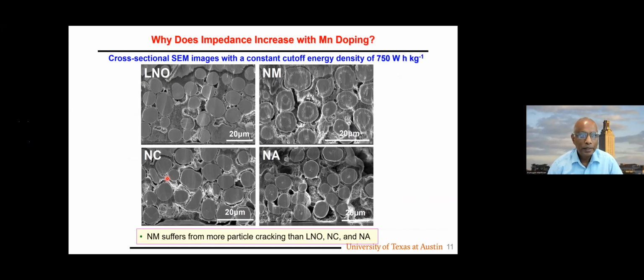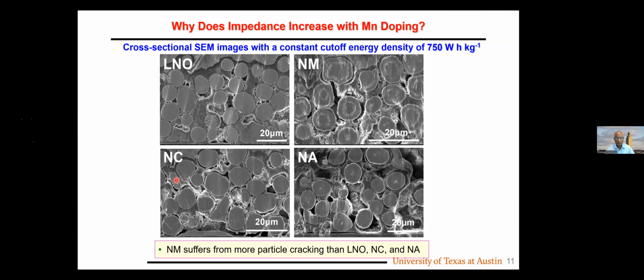So why does manganese cause more impedance? If you see the cross-sectional SEM here, you can see a little bit of cracks forming here, and NA maybe a little bit, much less. These two do not show any cracks. So the impedance increases obviously due to the crack formation. So the next question is, why does manganese doping lead to crack formation?